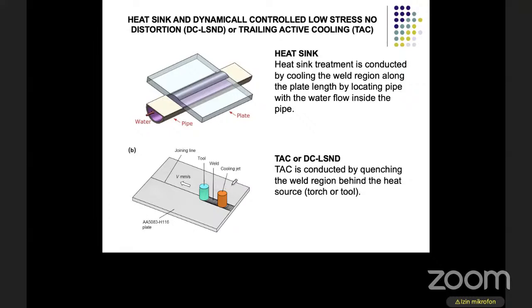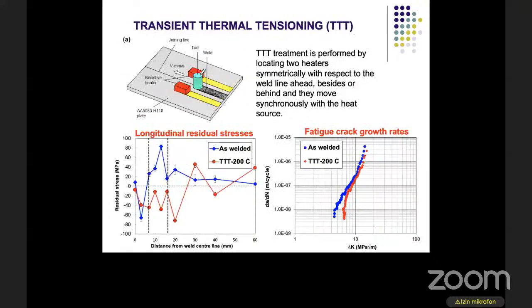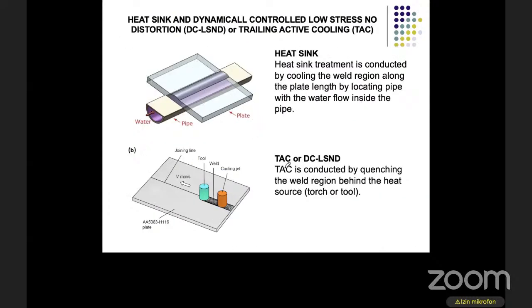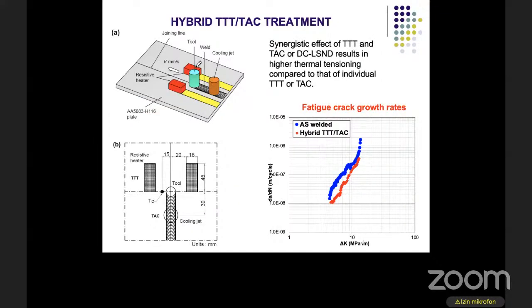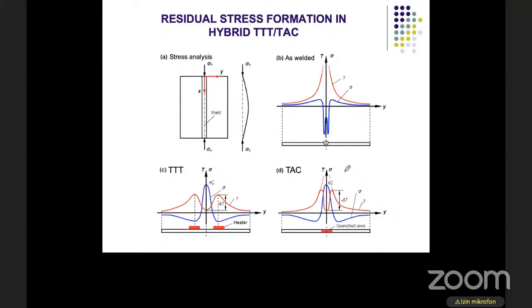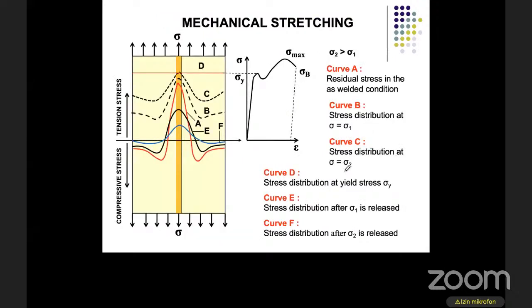And then we try to combine TTT, which is the heater here, and TAC, trailing active cooling here, and then it results in something like this. So we say that this is hybrid TAC and TTT. And here we found that this method is more effective compared to the individual TTT or TAC. We can see the significant reduction in fatigue crack growth rate in the weld metal region. And then this is the mechanism of how residual stress is reduced, and we propose it based on the previous reports from some journals.